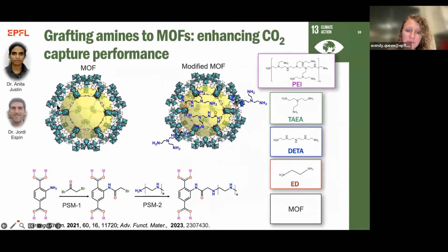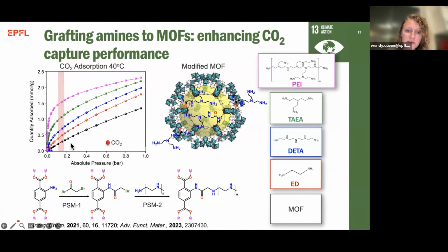And so here is the first material. We're learning how to decorate MOFs with amines. So what we do is we make our MOF. Here is our ligand, and you can see it's got an amine functionality. We then modify that with this bromoacetyl bromide, and this forms a bridge. And we can use this bridge then to covalently graft a variety of other amines, like the ones that you see here, like this ethylene diamine. We can increase the number of primary amines all the way up to polyethyleneimine, for instance. So here, basically what we've made is a MOF that's now modified with loads of different amines inside the material's pores. So let's take a look and see what it does to the CO2 adsorption properties.